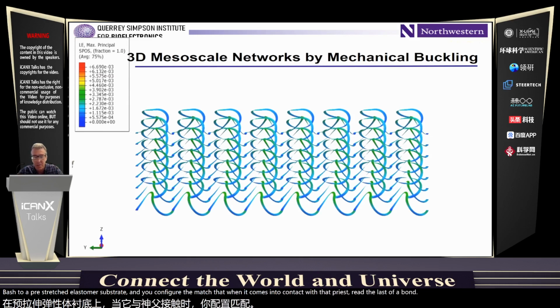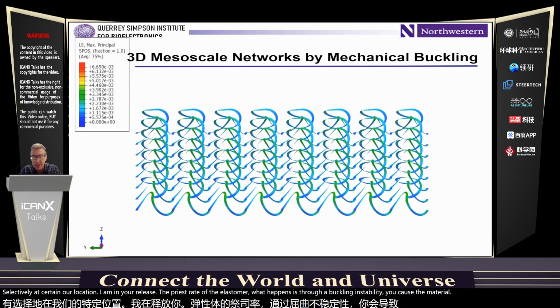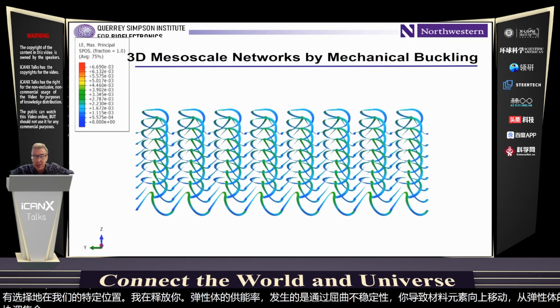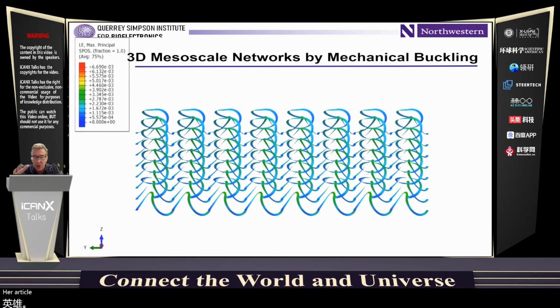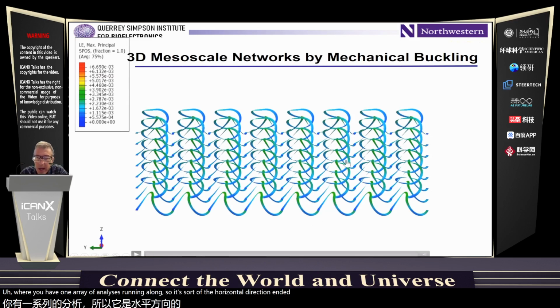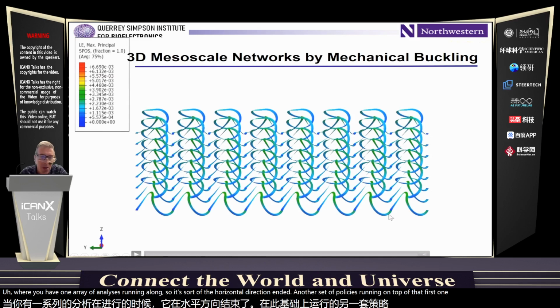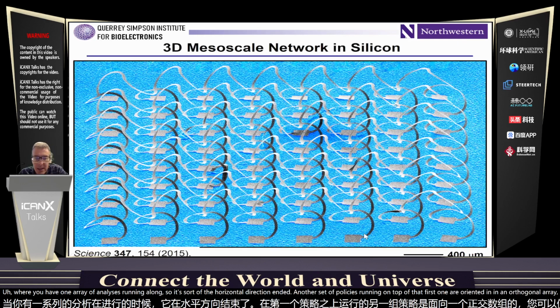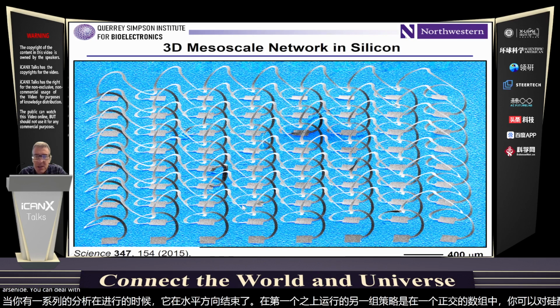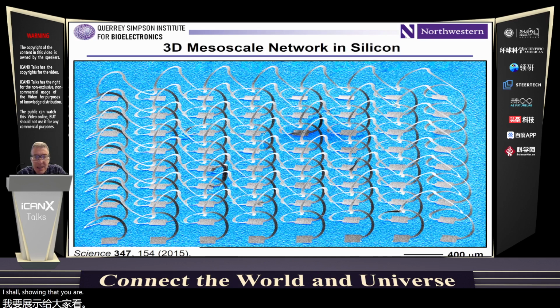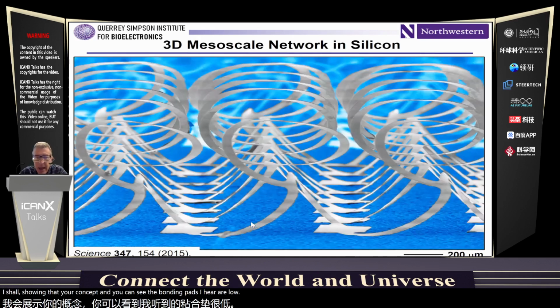What happens is, through a buckling instability, you cause the material elements to move up out of the plane of the elastomer, the surface of the elastomer, in a coordinated collection of rotational and translational motions, which for this particular example transforms that planar serpentine mesh into a hierarchical structure of helical coils. Where you have one array of helices running along sort of the horizontal direction, and then another set of helices running on top of that first one, oriented in an orthogonal array. And you can do that with silicon, you can do it with gallium arsenide, you can do it with fully formed systems. This is an example showing that concept, and you can see the bonding pads here locally, and you can see this in cross section.